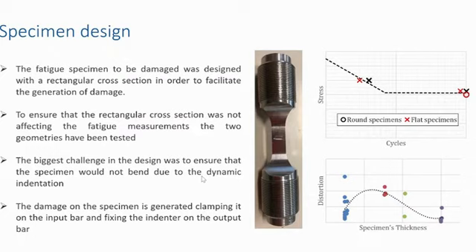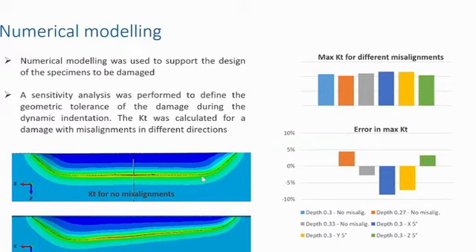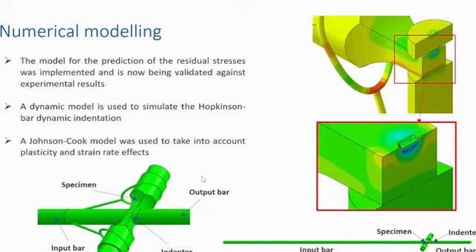And we did a sensitivity study on the thickness of the specimen. Also, to help the design, we calculated the KT along the damage through finite element analysis, where we take into account a small misalignment of the indentation to see if this was affecting massively the KT or if the specimen would start nucleating a crack still from the middle of the damage. And with this, we verified that the tolerances that we had in place were enough to guarantee a good repeatability of the damage. Last slide.